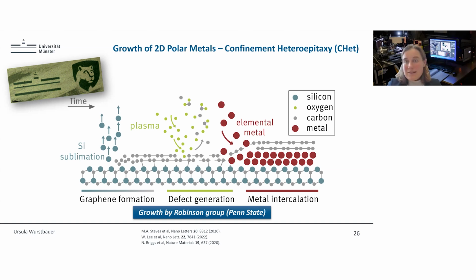And I would say the same applies to the second point, stress and strain. Yes, you have to think about thermal expansion coefficients for your materials. In the case of Van der Waals materials, it's not that crucial because due to the Van der Waals interface, they slide. So here it's easy; typically it's hard to transfer strain to the materials and not the other way around. But of course, also here we have to carefully consider it, and yes, strain might be there.